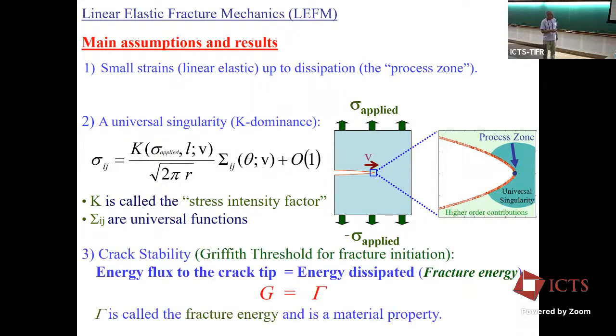Now, cracks are stable, so you can have a crack, and even though it has a singular stress at its tip, it won't necessarily move. And why? Because it's not transporting enough energy to the tip in order to break bonds, to satisfy the dissipation at the tip of the crack. So a crack will move when the energy flux, which we'll call G for reasons that I've never understood, the energy flowing in from the elastic fields into the tip of the crack, is equal to the dissipation. And this dissipation gamma is called the fracture energy, and it's considered to be a material property. So this is something that each material has.